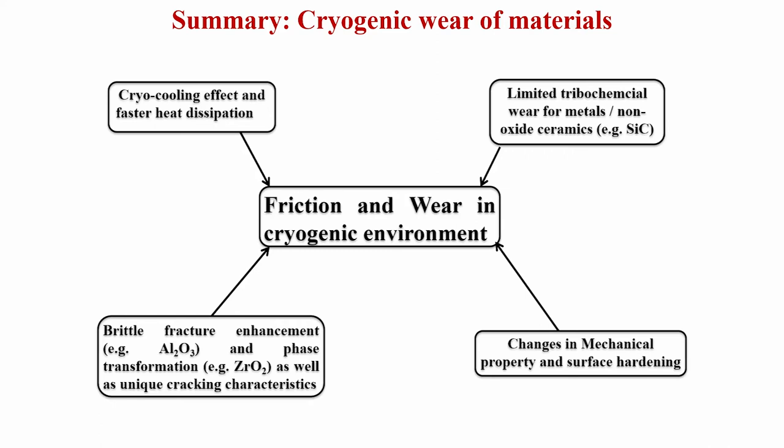So, what we have observed is that the differences in the wear mechanism can be attributed to a host of factors. Those include the cryocooling effect and faster heat dissipation. Second is brittle fracture enhancement, phase transformation and unique cracking characteristics. Third is the changes in mechanical property and surface hardening. And fourth, in the case of silicon carbide, limited tribochemical wear for metals or non-oxide ceramics, that is silicon carbide.